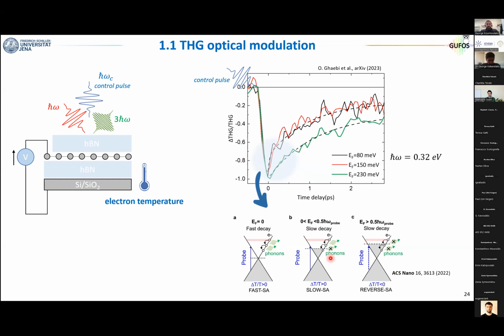However, if you now start increasing the doping, there will be a level where the final state where the electron should go is already occupied by another electron. This is a sort of Pauli blocking, or a phase space filling, or a phase space quenching. So in this case, you cannot emit an optical phonon anymore. And then, of course, this dynamic must be fully suppressed. And this is indeed exactly what we observe also in these third harmonic experiments.